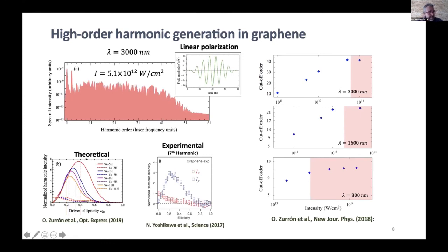We have also used polarized laser drivers in our simulations with agreement with recent experimental results. For example, you can check these two references where the harmonic yield is analyzed versus the polarization of the input field. But remarkably, our simulation shows that unlike other physical systems, the cutoff scaling saturates at the largest intensities, and it is not described by any simple law, linear or quadratic, as you can see in these panels.